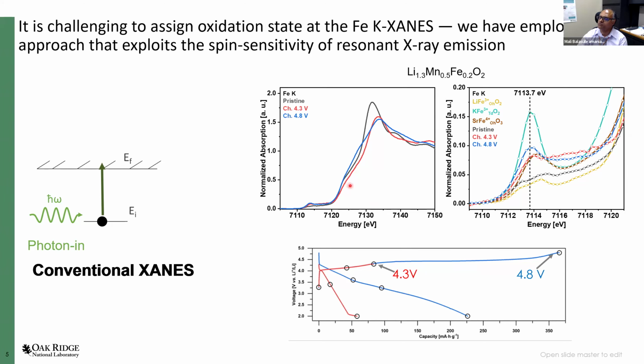Furthermore, the edge shifts are small, and the edge shifts, particularly in this case, are not very systematic. For example, when you go to 4.3 volts, the edge is shifted a little bit more than that at 4.8 volts, and we expect higher oxidation, or at least the edge remaining at the same place if the oxidation state does not change. However, we see that that is not the case.